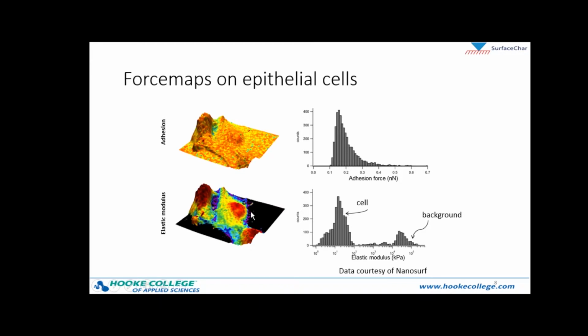And this is an example of this measurement done on epithelial cells. We can even build a histogram on this sample to really get some statistics and a quantitative value of what the adhesion is. Notice in the units of nanonewtons, and the modulus. The cells are quite soft, so this is kilopascals. And we can see here this was a modulus in this histogram of moduli. This is a modulus of the cells, and this is a modulus of the background, and thus get fairly quantitative measurements on these important mechanical properties of our sample, in addition to being able to image and get mechanical contrast from our sample, as I showed in the previous example on the tire tread.